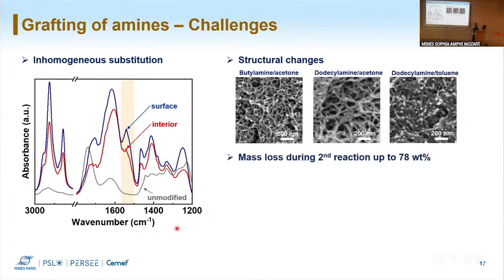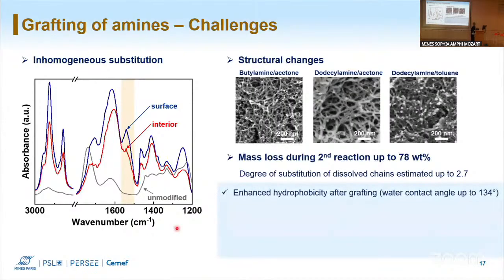And lastly, we saw that we lost a lot of mass during the modification. So when chains started to substitute a lot on the exterior of our material, they started to dissolve in the solvent. And for these dissolved chains, we could estimate a very high degree of substitution. So for these materials, in general, we could achieve enhanced hydrophobicity. We could reach very high contact angles, even with not as high degree of substitution.